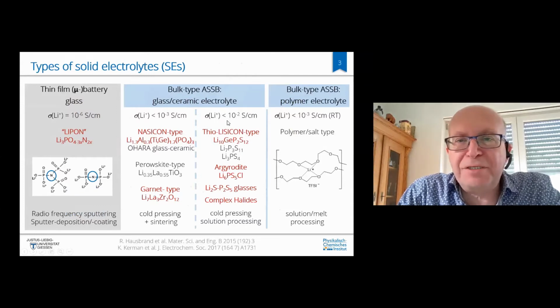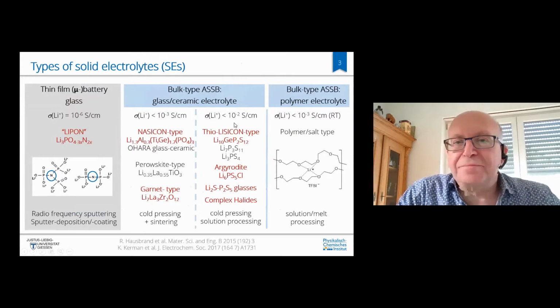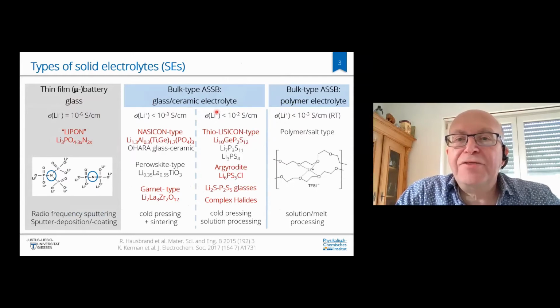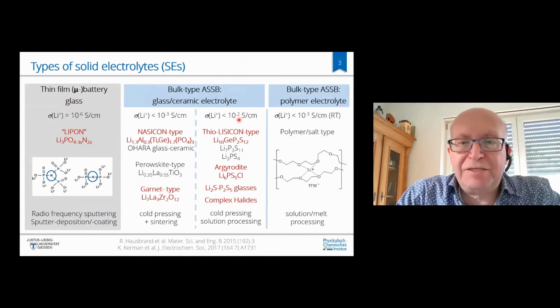I think what is important is today we have solid electrolytes that have lithium-ion conductivities that are higher, in fact, than the liquid electrolytes. So we can achieve with the sulfide electrolytes conductivities of 10 millisiemens per centimeter and more. So the conductivity of solid electrolytes today is not limiting.